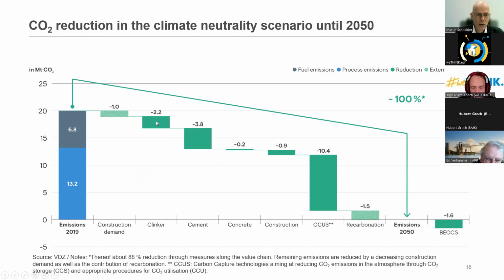Now, why is this so limited, so small? The reason is that we are already applying a high degree of alternative fuels, with the respective content of biomass. If you draw this picture for countries where you start using alternative fuels, the contribution here is much bigger. So it depends on the reference time here, and the question, what was the substitution rate at that time? Now, I'm not going to repeat what I've shown you. The clinker factor reduction here is, and then at the end, of course, the use of carbon capture and the subsequent utilization of the CO2 or its storage.